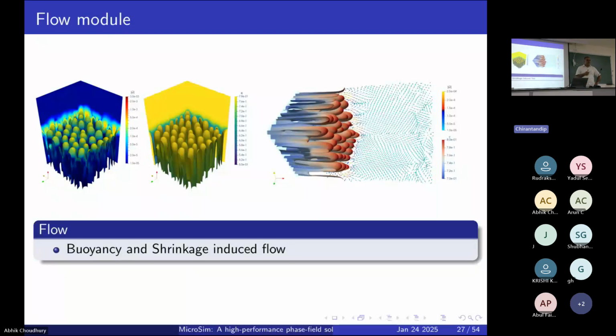And it leads to certain defects which are very detrimental for the crystal growth. For example, freckles. Freckles are defects where you have got a channel formation where the morphological evolution starts to stabilize with the channel, and the channel is going to remain as a defect later on. So such a blade is of no use. You have to just throw it.